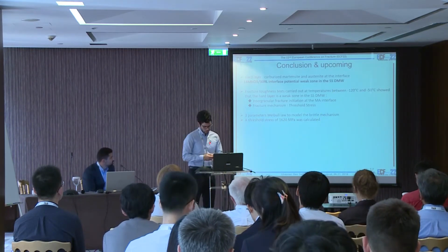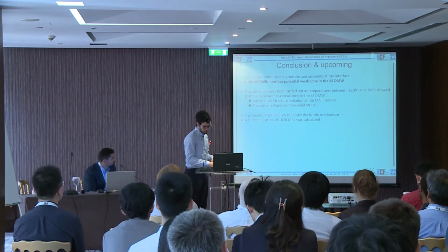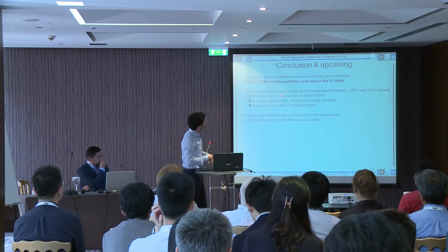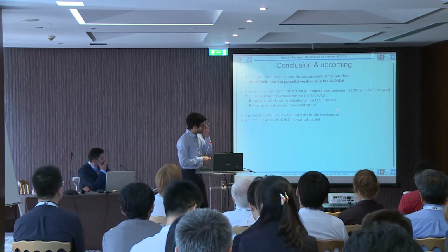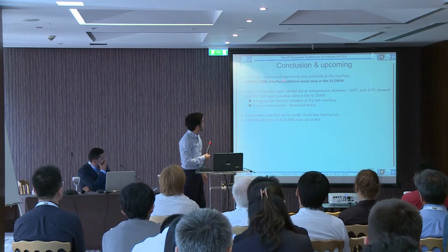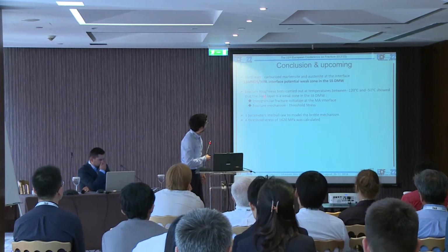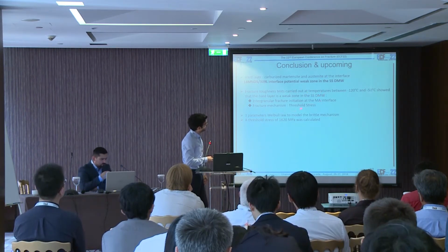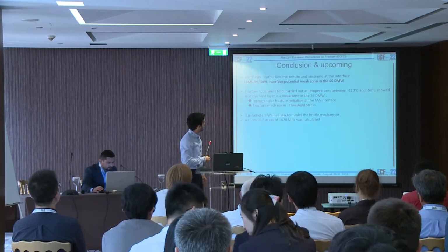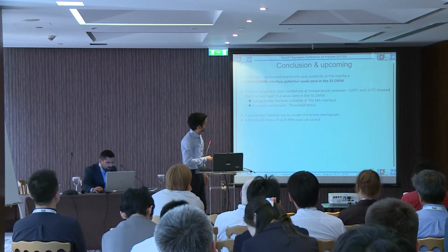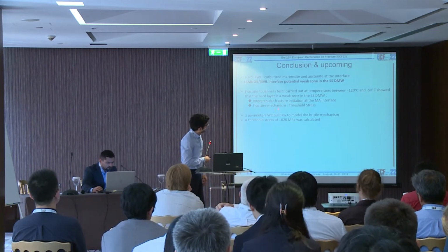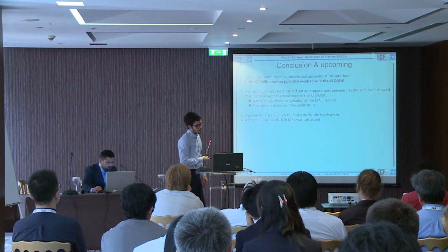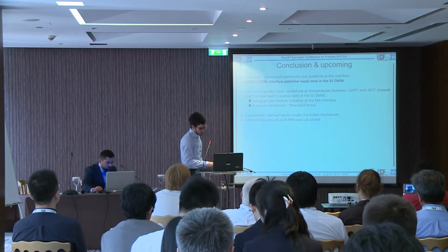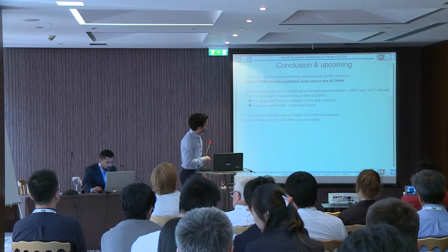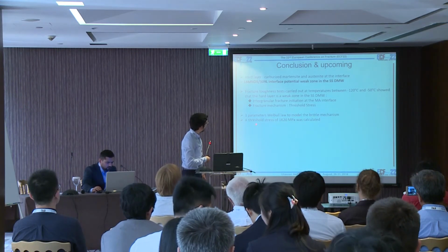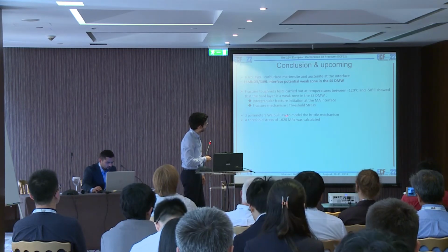So here are some conclusions and upcoming work. So we showed that in the SSDMW, the weakest zone is this hard layer composed of carburized martensite and austenite. Fracture toughness tests carried out at low temperatures showed that this hard layer is a weak zone, showing intergranular fracture initiation at the MA interface. And this fracture mechanism seems to be consistent with a threshold stress. So in the last part, with the 3-parameter Weibull law, we modeled this brittle mechanism and we identified the threshold stress, this value.